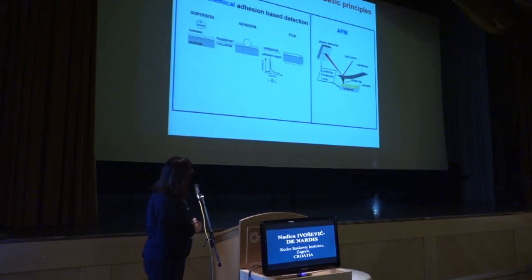Basically, when we have a soft particle in our aqueous electrolyte solution, we have our charged electrode system. Stochastically, when a particle collides with the electrode and makes attachment, it sweeps the charge from the interface, and then this deformable particle deforms and spreads over the interface, forming a film of monomolecular thickness.